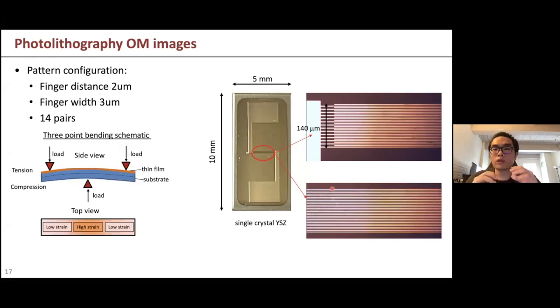So how are we going to strain the sample in situ? We chose bending as the method. Here I'm showing a 3-point bending schematic to show how it should look. For 3-point bending, of course we have 3 points. We have a loading point in the middle, and then we have 2 supporting points that basically hold the sample. And if we are bending a beam, we have to look at the neutral axis. Above the neutral axis is in tension. Below the neutral axis, it is in compression.